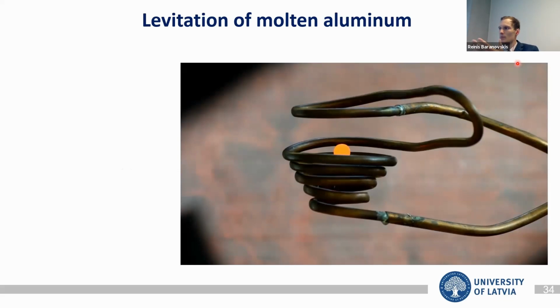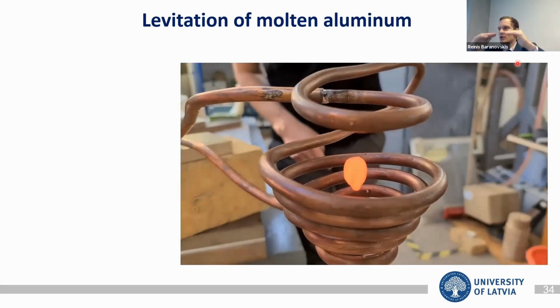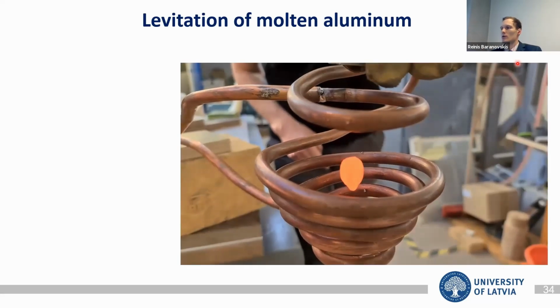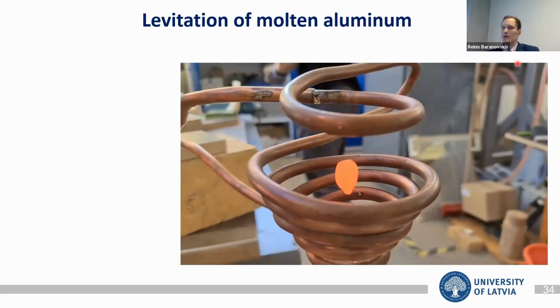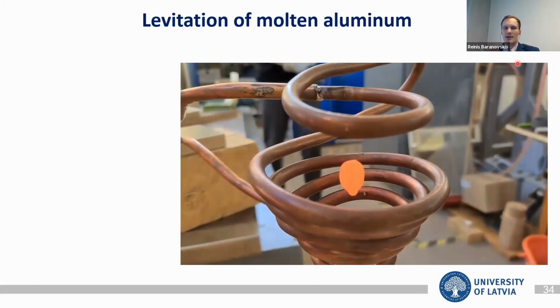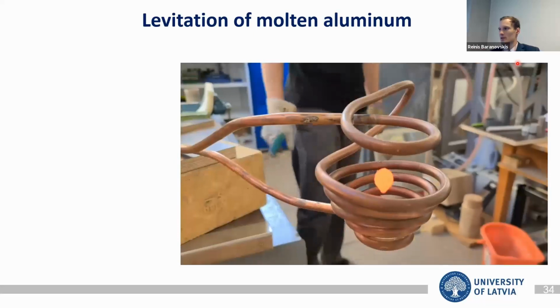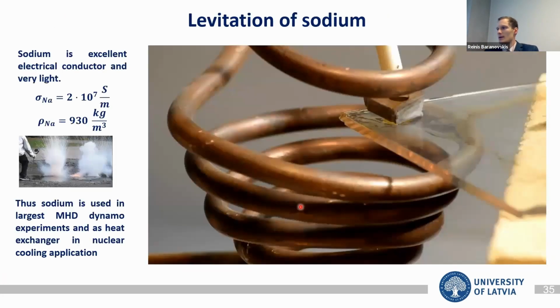First, it heats up as well. And when it heats up, it even drops in the levitation coil since the electrical conductivity has dropped as a function of temperature. And filming this was quite interesting. It looks like I've added this in CGI and post-processing. The camera, it's really difficult to capture this effect accurately. I'll try to put it to video again.